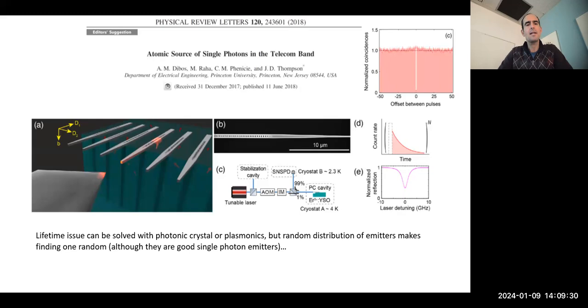Okay, so here's an example of a work that was done by the Princeton group, and what they've done is they're looking at these erbium emitters in these photonic crystal cavities. They made several of these cavities, and the erbium emitters are randomly implanted or distributed within this crystal. The issue here being that in some of the cavities, you're going to have just one emitter. In some, you'll have multiple.